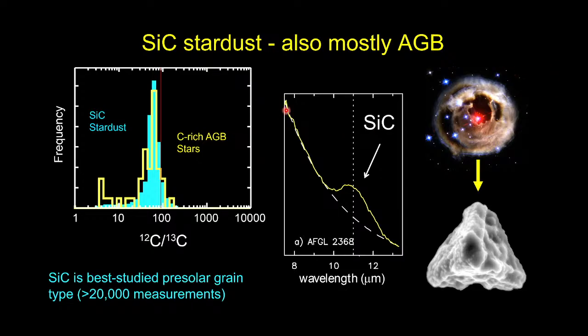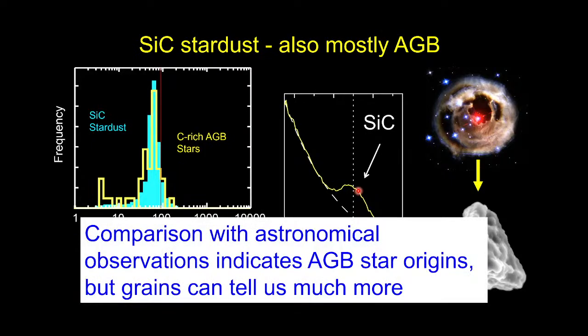You also see silicon carbide in AGB stars directly from the infrared spectra, that there's a feature at 11 microns. So this is a presolar grain from a meteorite, but imagine this crystal in this AGB star basically absorbing light from the very hot central star that's becoming a white dwarf. That light is absorbed by the silicon carbide and then re-emitted at 11 microns. And we can see that and say, oh, there's silicon carbide there. So a nice connection between the astronomy and the laboratory work.